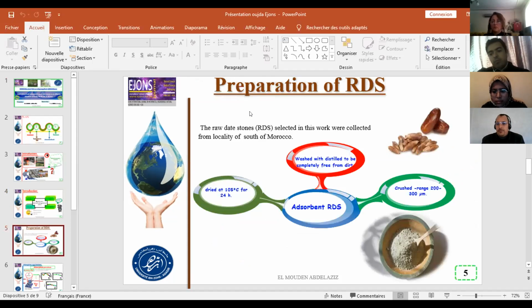As we know, the presence of heavy metal in water, even in trace amounts, is environmentally hazardous. There is an imperative need to develop innovative and environmentally friendly material for their removal from wastewater. The present study is concerned with the valorization of date stone for wastewater treatment. Date stone as adsorbent was tested for adsorption of copper, lead, and zinc from aqueous solution. The effect of different parameters on adsorption of metals, such as contact time, the initial concentration, and the pH of solution, were investigated, showing an efficient adsorption exceeding 95% toward copper, lead, and zinc when their concentration was lower than 10 ppm, and from 60 to 94% for metal concentration higher than 10 ppm.